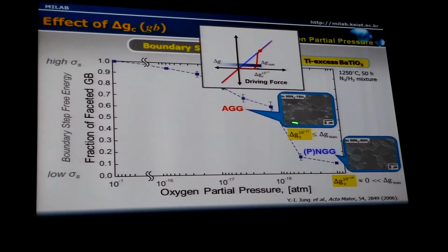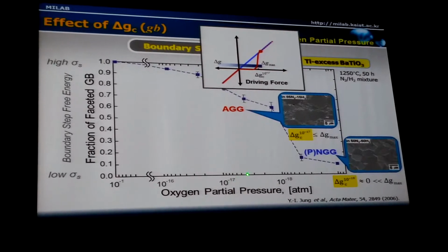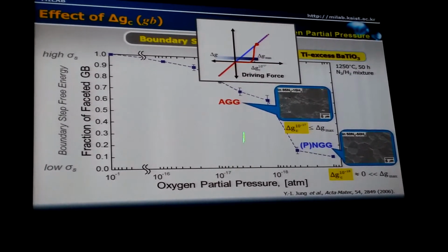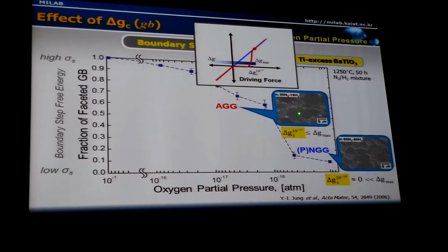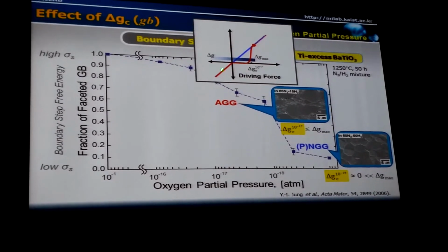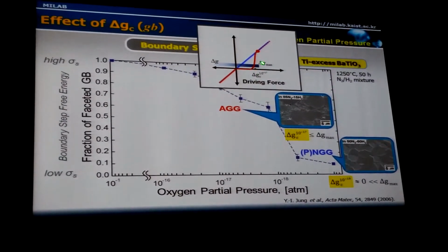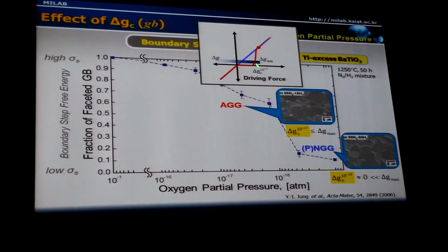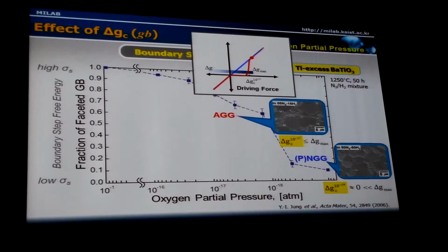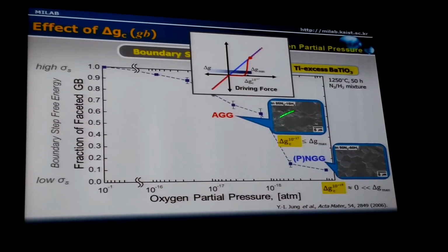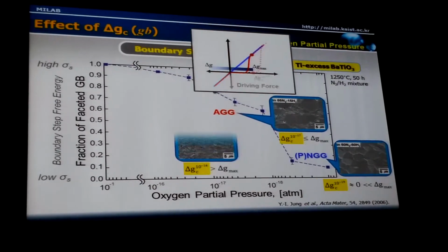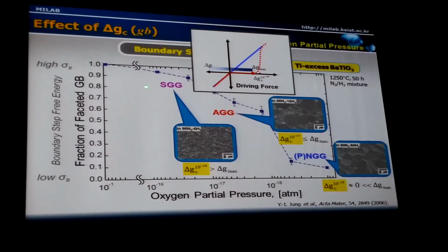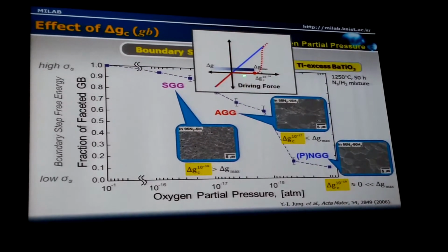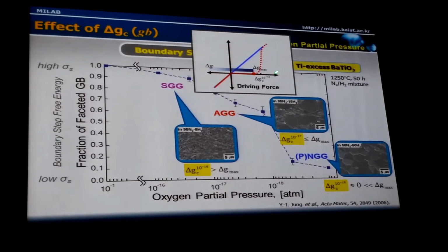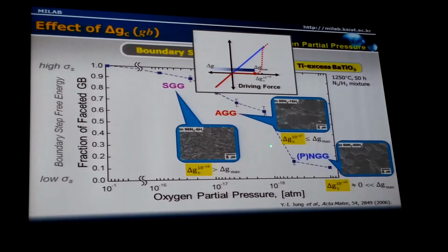And then at an oxygen partial pressure of about 10 to the minus 17, abnormal grains formed. That means the critical driving force increased, although the maximum driving force was the same because we started with the same powder, and then abnormal grains formed. And with the increase of the fractional faceted boundaries, the critical driving force increased further, and stagnant grain growth appeared.